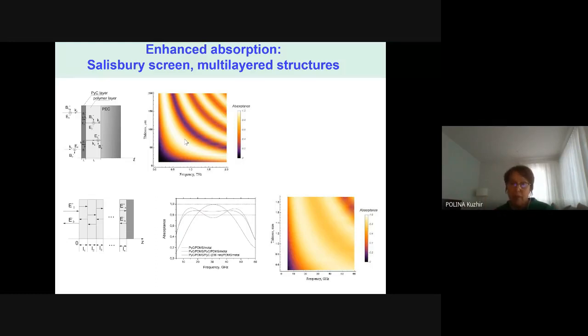you could organize the sandwich structure and again put it on top of the back reflector. When the radiation comes from the graphene side, this was achieved experimentally, you could have absorption at the level of 90% for a very broad frequency range.